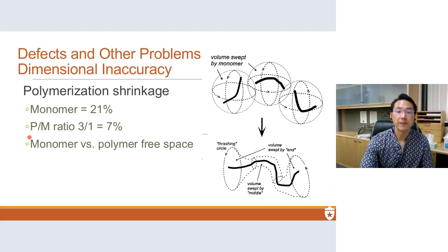If we use a polymer to monomer ratio of 3:1, the polymer beads, most of it actually does not react. So you really only have a third or a quarter of the monomer reacting. And that's why the shrinkage is reduced to 7%. And it's, again, because of the monomer to polymer reduction in the free space.